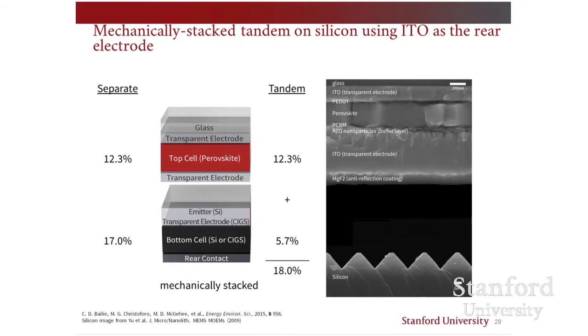A few years ago, my group set out to demonstrate that all of this was possible, and the easier one to make is the mechanically stacked tandem, and that's what we did. Back then, our perovskite only had 12.3% efficiency, and we put it on top of 17% efficient silicon, and we also had 17% efficient CIGS. And when you put those under the perovskite, the efficiency, of course, drops because a lot of the photons are absorbed in the top cell, but you could still get 5.7, and if you add those up, you get 18, which is better than either cell by itself.